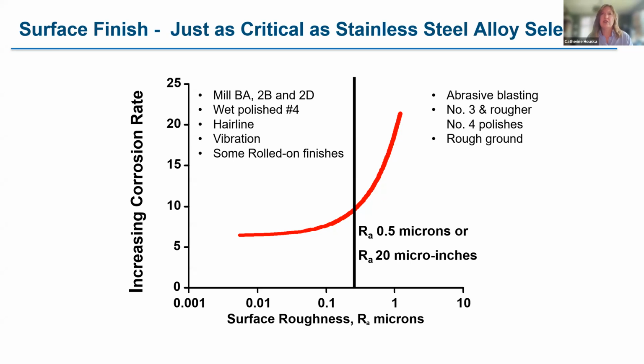There's been quite a lot of research on the relationship between surface roughness and corrosion performance, mainly for industrial applications. I've done some myself for some of the polishing houses. But the general rule of thumb is that if you have a surface roughness of RA 0.5 microns or 20 microinches or less, then you will have a much lower corrosion rate. So those smoother finishes will need less cleaning, they'll accumulate less dirt, salt, whatever is in the environment, and they will perform better. If you really think you need a rougher finish, if you aesthetically have to have abrasive blasting, then the corrosion rate will be a lot higher, and you might need to use a more corrosion-resistant stainless steel to achieve an acceptable aesthetic finish.